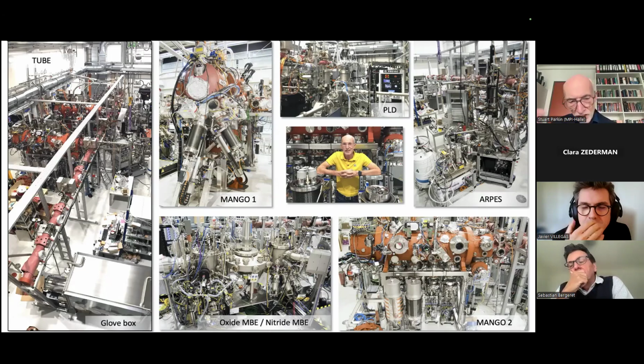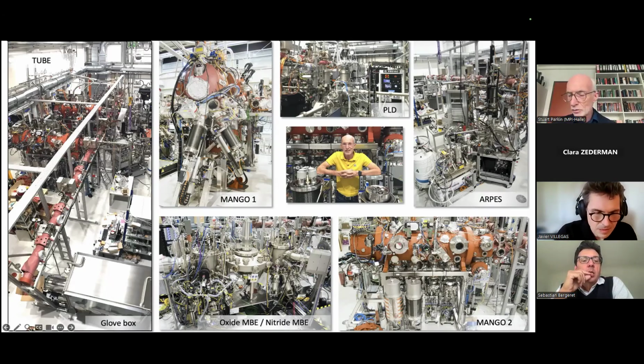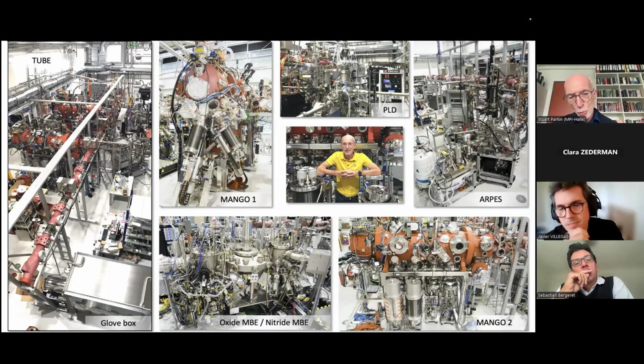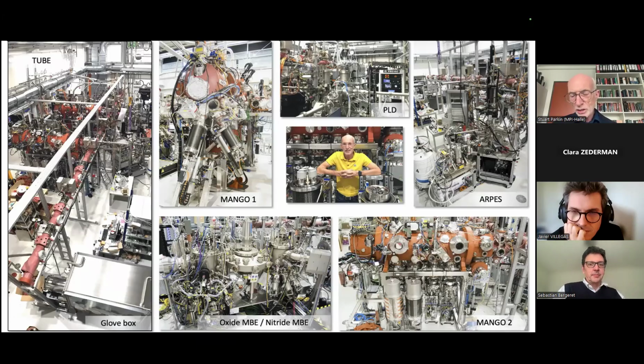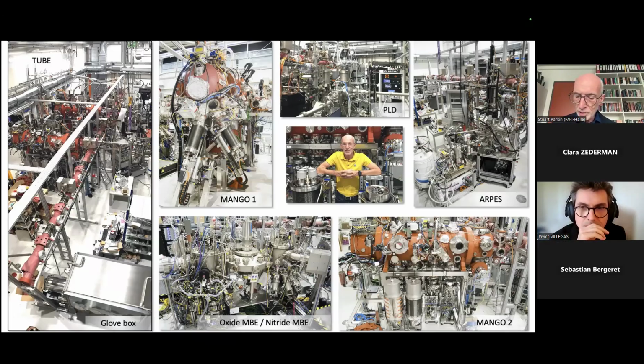And then all these systems are connected. On the left-hand picture, you see this orange line. This orange line is a UHV, ultra-high vacuum tube, 15 or 16 meters long, through which we have a little robot that carries substrates under automated control, and we can switch the substrate between these different systems, again under robotic control. So we think this is one of the most advanced systems of its type, enabling us to build very complex systems. And then down below we have a glove box, and this I'm going to show you later on. We use that glove box to exfoliate 2D van der Waals materials.